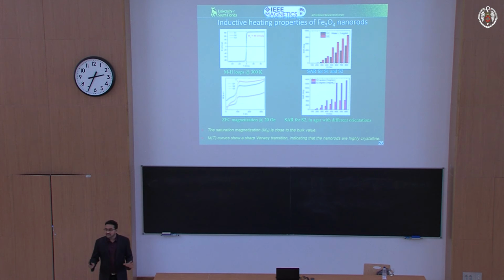You will never see it in nanoparticles if they are of low quality. So this can be used as a quality check. If you want to make high quality magnetite, look for the Verwey transition. And if you find it, chances are you've got very high quality single crystalline nanoparticles.